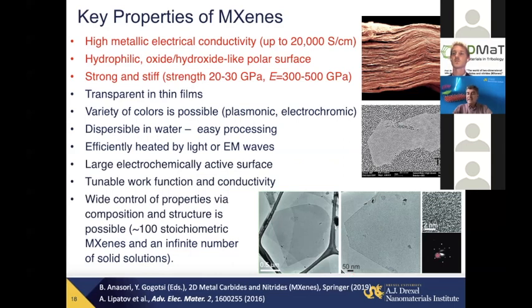And they are again single crystals. I mentioned already their stiffness. For example, graphene would not hang in a hole of a TEM grid this way. It would collapse because it's very flimsy. MXenes with several layers of transition metal are significantly stiffer. But you can also make a thick film. For example, this is a couple of micron film. It means that there are more than 1,000 monolayers in this film. Again, very similar to graphene.